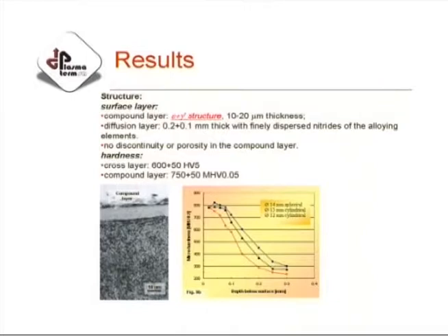And the cross-layer hardness of about 600 Vickers, and the compound layer has roughly a hardness of over 750 to 800 Vickers. And we give here a typical micro hardness plot in 3 different positions of the shaft. So that means that we achieve very well the technical goals with this new technology. And the steadiness of the results, the reliability was excellent, was better than in case of carburizing.